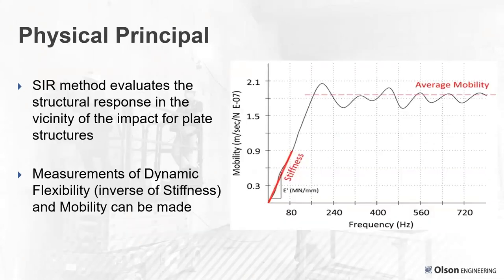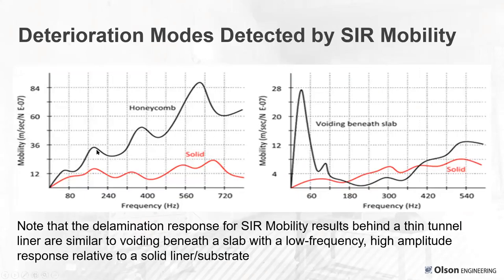The method uses a typically 3-pound instrumented impulse hammer measuring impact force, and a geophone or velocity transducer (an integrated accelerometer) for use on tunnel liners, since geophones are only designed to work when fairly close to flat. You measure force and vibration response — it's really a modal vibration test. You can evaluate about a foot and a half deep. The ASTM standard C1740 covers both subgrade void evaluations and structural concrete evaluations. It evaluates structural response measuring dynamic flexibility (inverse of stiffness) and mobility (velocity over force). On a mobility plot over 0–800 Hz, the low-frequency part represents stiffness, and higher mobility indicates comparatively poor support conditions.